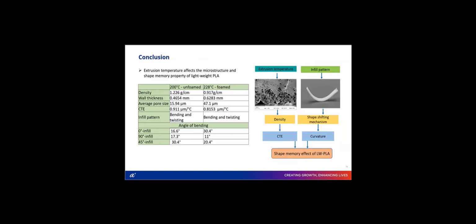Overall, from our research, we conclude that for the same material and the same process, by altering the extrusion temperature we obtain different microstructural morphology, which affects the density of the part and the coefficient of thermal expansion. Combining it with a different infill pattern, we obtain a different shape-shifting mechanism and bending angle, which overall affects the shape memory effect of the lightweight PLA. By understanding the relationship between microstructure and process parameters, we can print the same structure with a different shape memory performance.